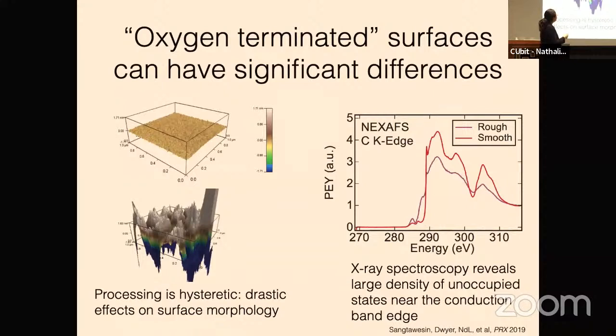So the first is that we immediately discovered that the whole community was using oxygen-terminated diamond to make charge stable NV centers, but what you call oxygen-terminated varies drastically depending on what exactly you did. And more to the point, you could do the exact same chemical treatment to different surfaces and get drastically different surfaces. So for example, oxygen etching of diamond tends to be very hysteretic. So extremely small differences in the surface quality to begin with can lead to drastic morphology differences at the endpoint. So these are two things that went through the same process, but one of them has the fancy polishing and one of them has the less fancy polishing. And you end up with these giant kind of hills and valleys.